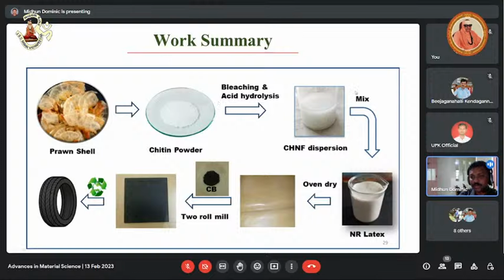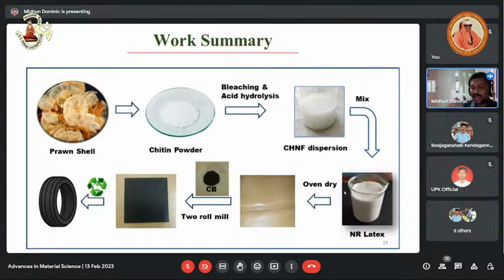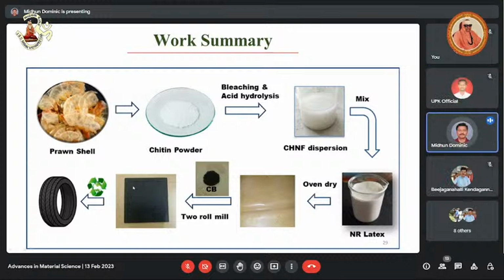So this is the chitin nanofiber dispersion that we prepared from prawn shell, and this chitin nanofiber is first dispersed in natural rubber latex. In the other two cases, in the case of silica, we directly added carbon black and silica in a 2-roll mill. Here the situation is different. At first, we have a uniform, highly dispersed chitin nanofiber in NR latex, which is oven dried. We make a sheet, and it is mixed with carbon black in a 2-roll mill, and we analyze the properties.